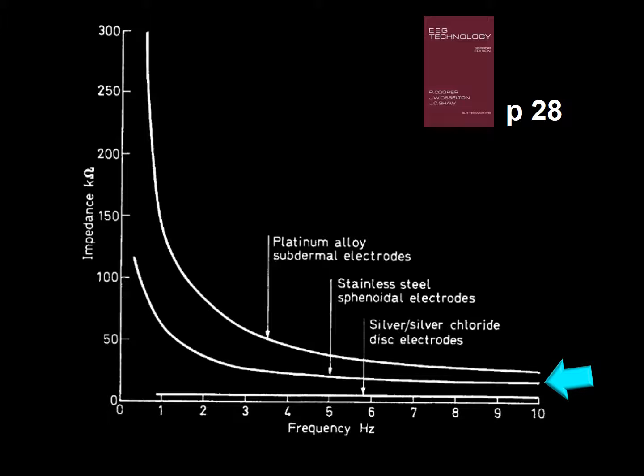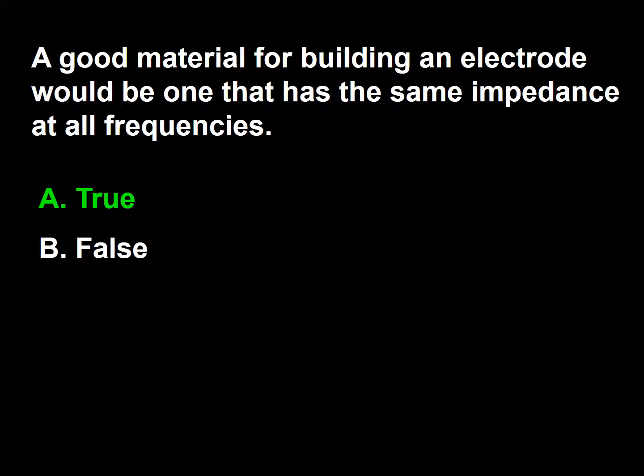impedance of silver chloride surface electrode, but it is much higher at 1 Hz. The difference in impedance related to frequency is even more noticeable when using platinum alloy. So the answer to this question is A.